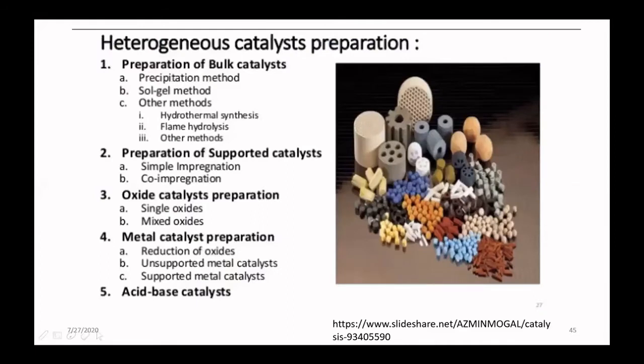Okay, there is catalyst preparation, both bulk and supported catalyst. For bulk catalysts, the methods are sol-gel, hydrothermal synthesis, flame hydrolysis, and for preparation of supported catalyst, mostly impregnation. Oxide catalyst preparation: single oxide, metal mixed oxide, more than one. We have also experience combining silica and zirconia. Metal catalyst preparation: reduction of oxide, for example nickel oxide into nickel zero, and supported metal catalyst, acid-base catalyst. This is the preparation of heterogeneous catalyst.